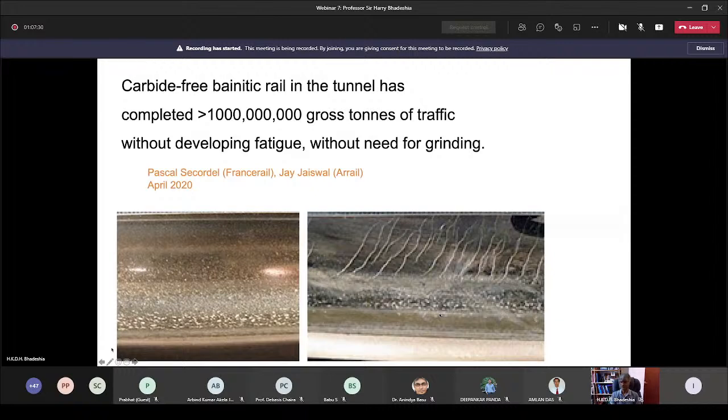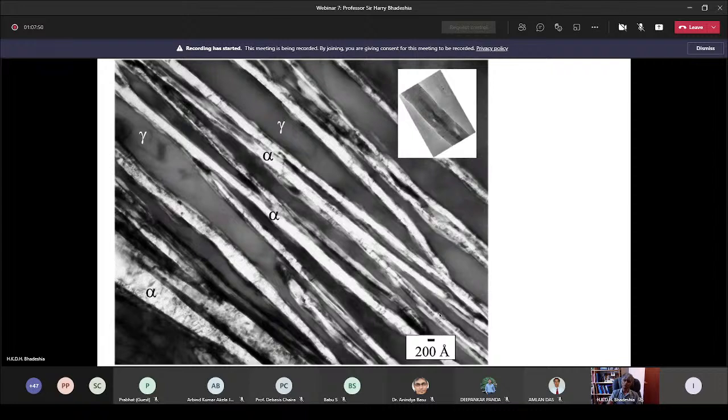So this is the Bainitic rail steel, and this is the conventional steel. So I should really end the story here. But there is a huge amount of potential in using the actual atomic mechanism of transformation in order to design a novel steel. And I'm not going to go into any detail, but some years ago, we made the world's first bulk nanostructured material, where the Bainitic plates are finer than carbon nanotubes at the same magnification. So these are plates in three dimensions, they're not tubes.